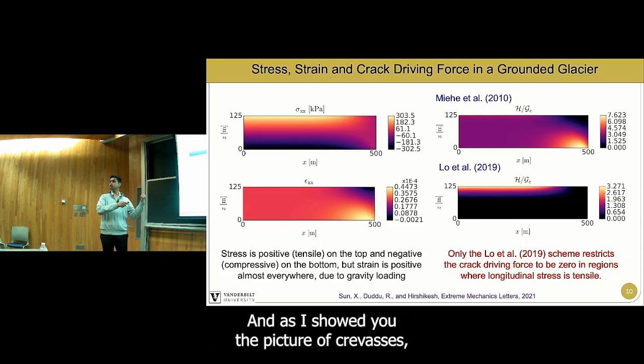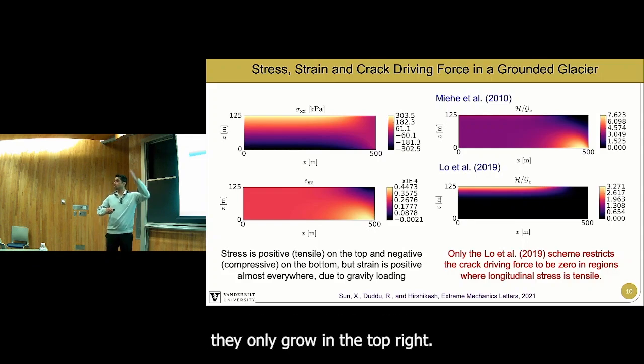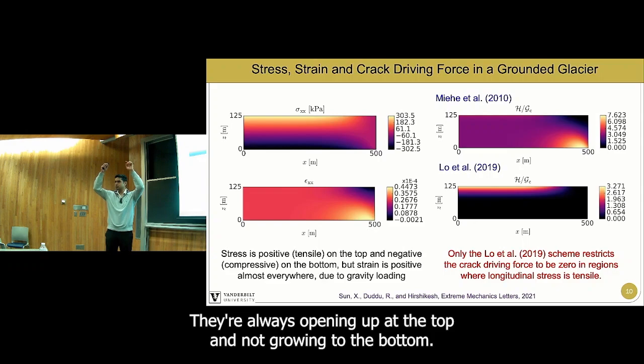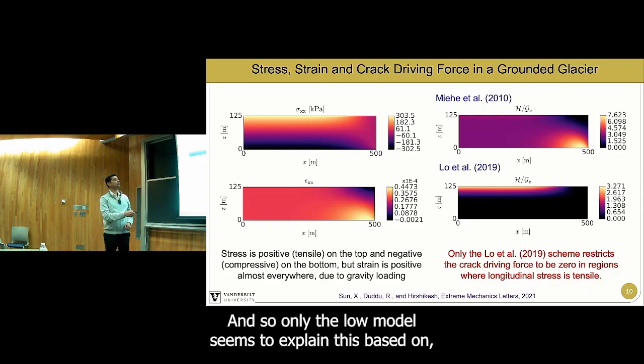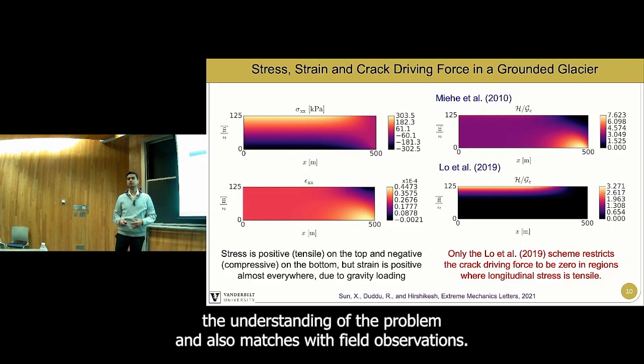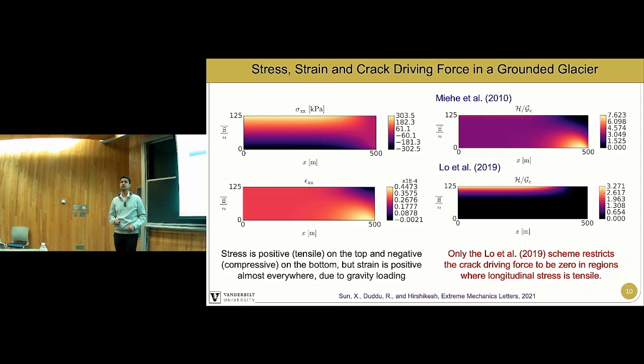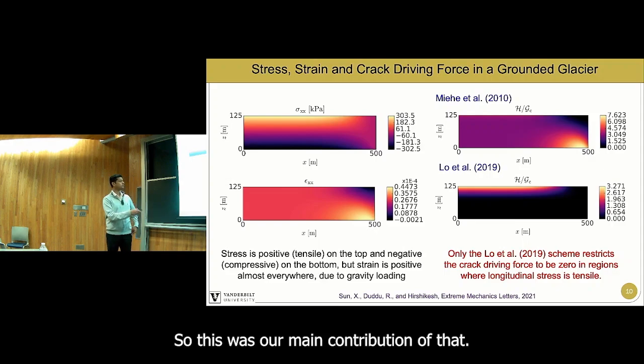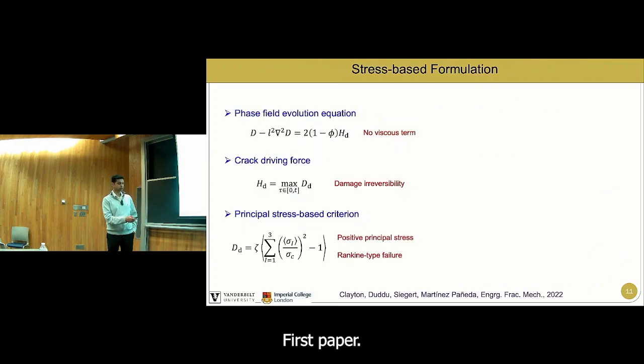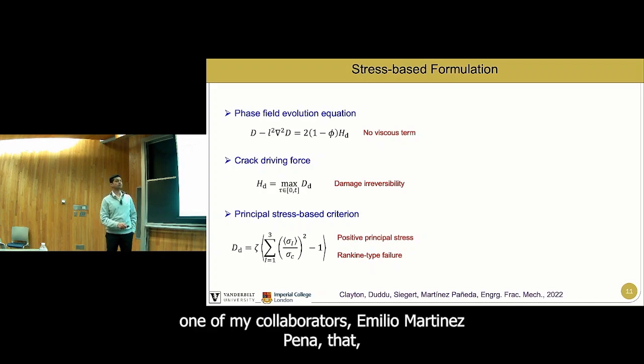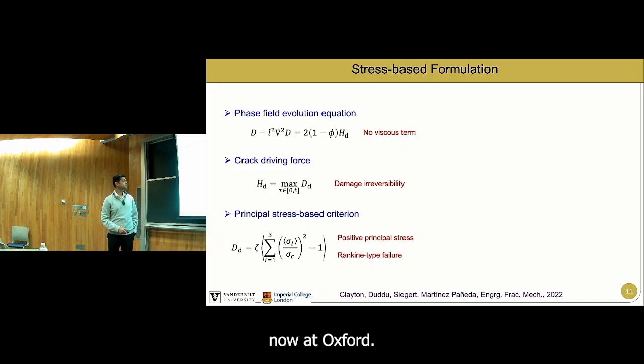And as I showed you the picture of crevasses, they only grow in the top, right? They're always opening up at the top and not growing to the bottom. And so only the Lo model seems to explain this based on the understanding of the problem and also matches with field observations. So this was our main contribution of that first paper.